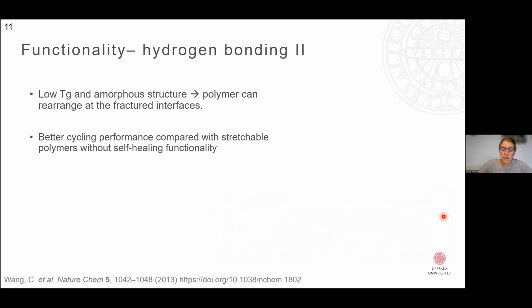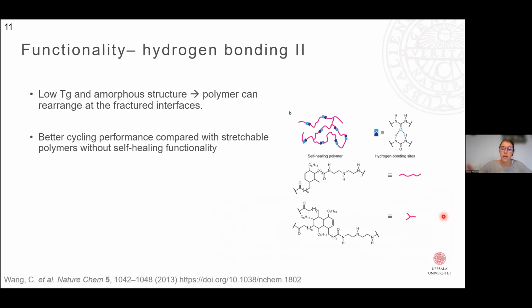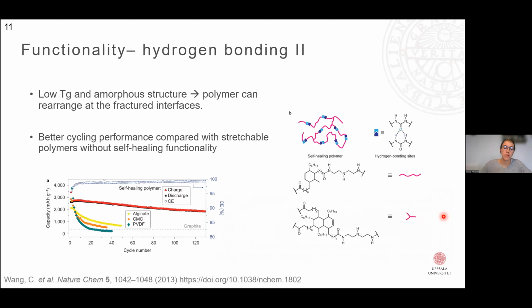Another example of hydrogen bonding is this, where they have used a randomly branched hydrogen bonding polymer with an amorphous structure and a quite low glass transition temperature, which the authors claim makes it easier for the polymer chains to rearrange where the fractured interfaces are. And the bonds are very easy to form and break in the system. They also show better cycling performance, compared to two different binders, but also compared with a more stretchable polymer without the self-healing functionality, to indicate that the improved capacity comes from the self-healing groups and not the polymer just being stretchy. In this paper, they have also shown an interesting evaluation of the self-healing properties. And this one they will talk about later after the Q&A and after the break. So you will hear more about that.